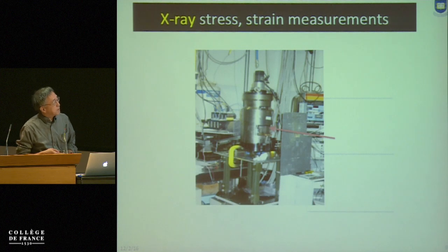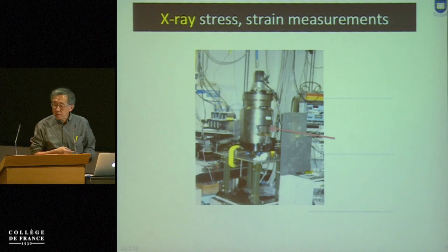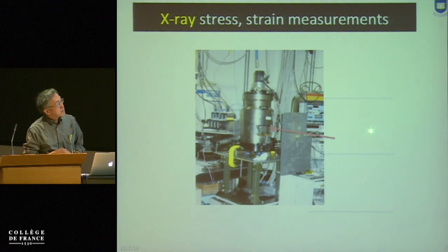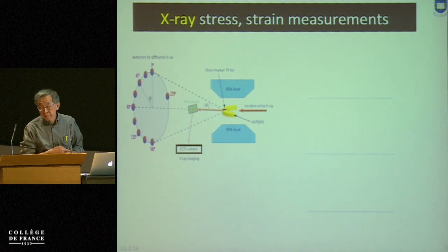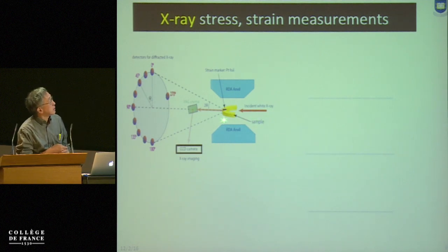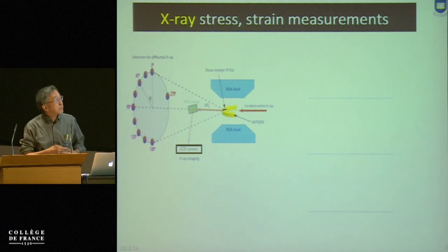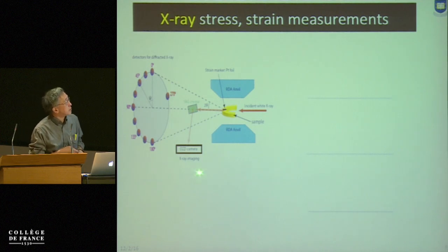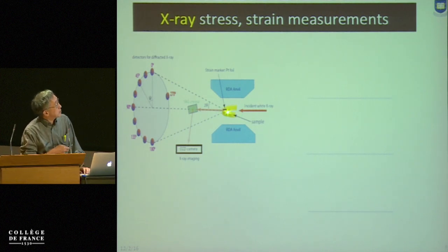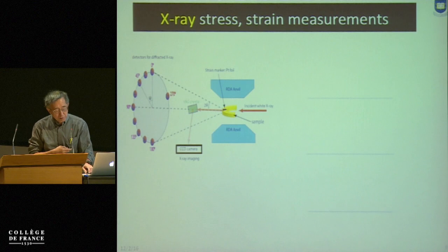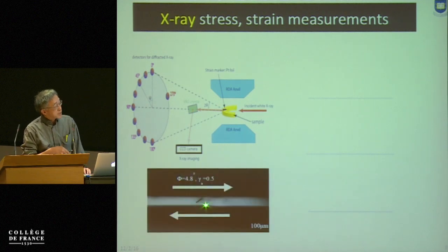So for the X-ray measurements of stress and strain, you put your equipment into the synchrotron facility, and then X-rays go from the beam line through your specimen, and the X-ray does two things. One is we collect just the image, like a medical X-ray, okay? And the image tells you something about the shape of your sample, from which you can determine the strain. And we collect diffracted X-rays as a function of orientation, from which you can estimate stress.